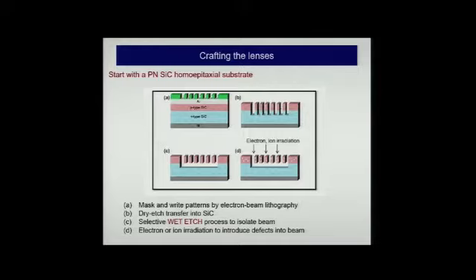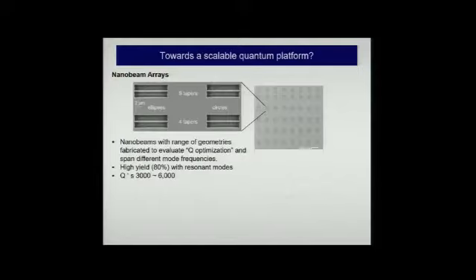The idea is we start with a PN junction. We use electron beam lithography to pattern the main features. We achieve the optical isolation through a dopant selective wet etch to make this undercut possible, and a wet etch so that we minimize the amount of ion assistance or electron assistance. And then finally, when the nanobeam is completely fabricated, we add the additional defects, the defects that we deliberately try to add by electron or ion irradiation.